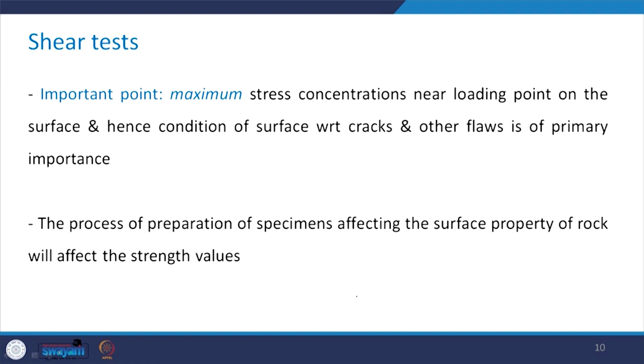The important point from the outcome of these tests is that there is no normal stress on the shearing plane. Neither the single, double, nor punched shear tests had normal stress on the shearing plane. So, the maximum stress concentration occurs near the loading point on the surface, and therefore the condition of the surface with respect to cracks and other flaws is of primary importance.